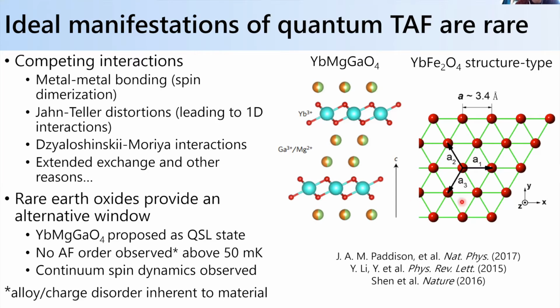And so, measuring this system down to the lowest temperatures, there's no real order observed above 50 millikelvin. And if you look at inelastic neutron scattering, one of the signatures people look for is the absence of well-defined spin wave modes or spin excitations. They look for signatures of spinons, for instance, if you were to have a quantum spin liquid state. And so there was some continuum spin dynamics observed in the system, which really drove a lot of follow-on research.